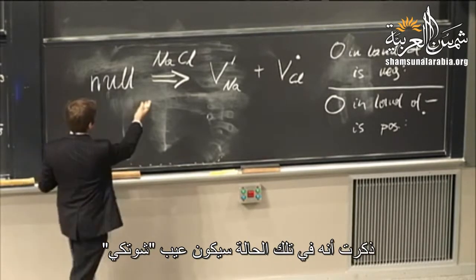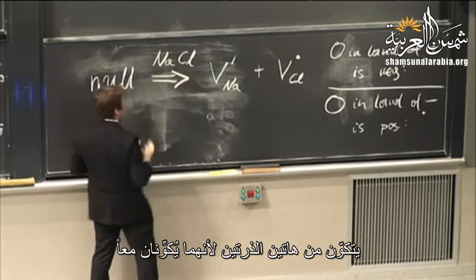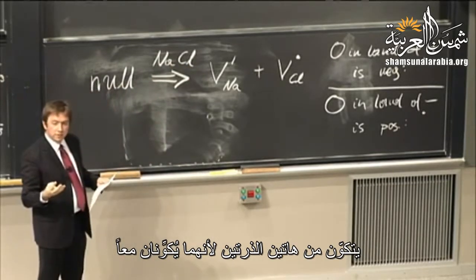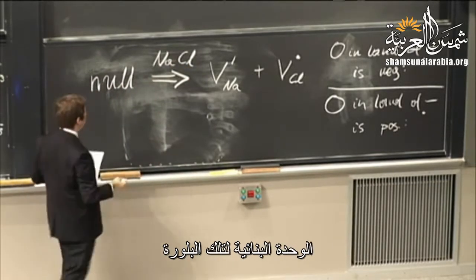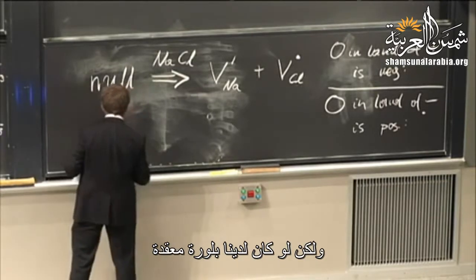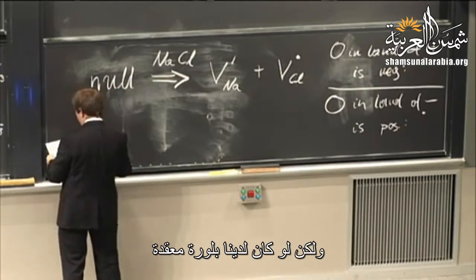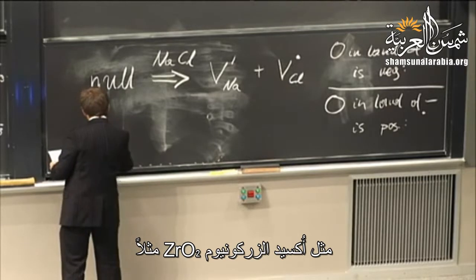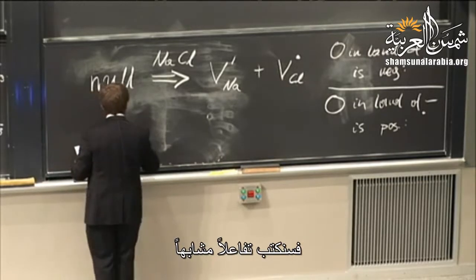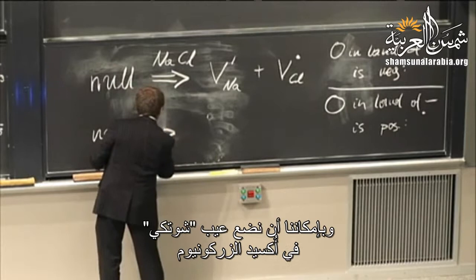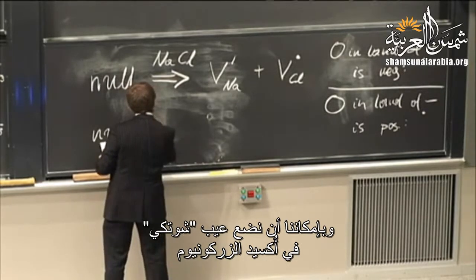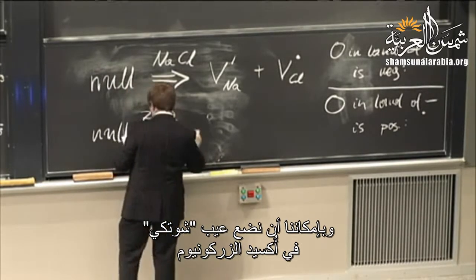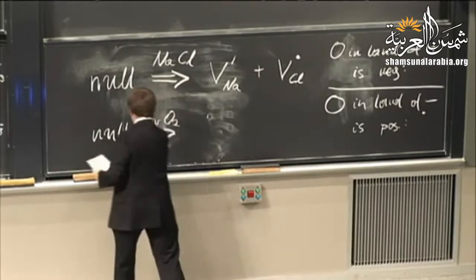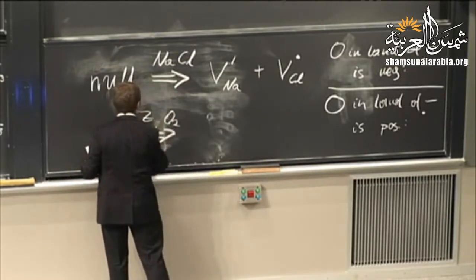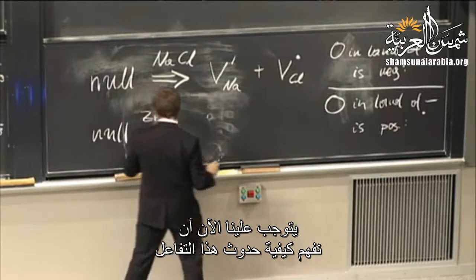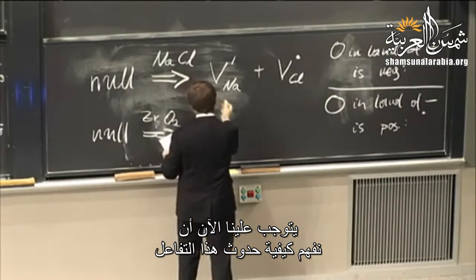So I mentioned that in this case, a Schottky defect would just be composed of these two atoms, because these two atoms constitute the structural unit for this crystal. But if we had some other more complicated crystal, like, for example, zirconium oxide, then we would still write down a similar reaction. So we could put a Schottky defect into zirconium oxide. Okay. And so now we have to figure out how this reaction plays out.